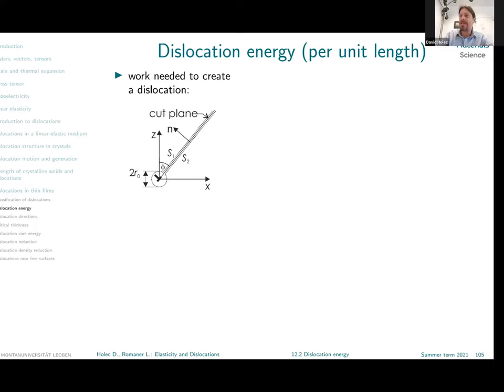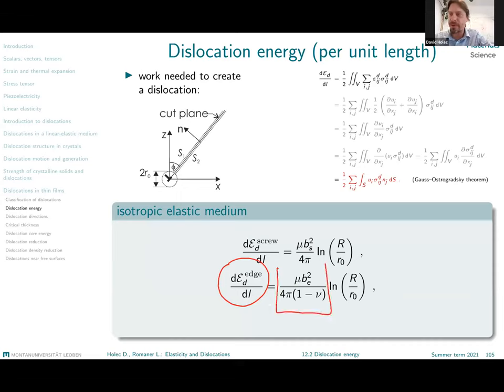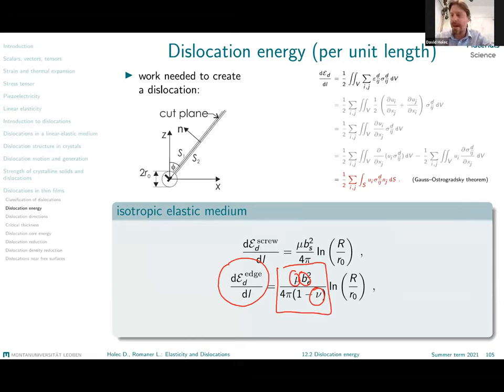I believe that you have discussed with Lorentz the possibility to calculate the dislocation energy. As a repetition, the dislocation energy for a pure edge dislocation is given by some pre-logarithmic term which depends on the edge component of the Burgers vector, on the shear modulus, and on the Poisson's ratio — this is in the approximation of elastically isotropic material. After that we have a term which expresses the volume which is elastically strained around the dislocation.